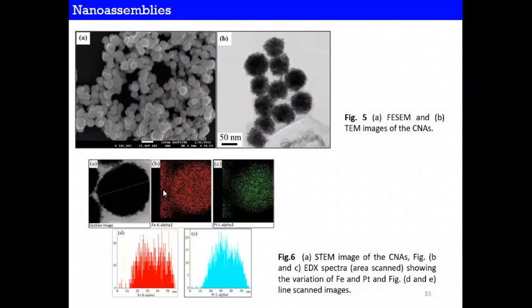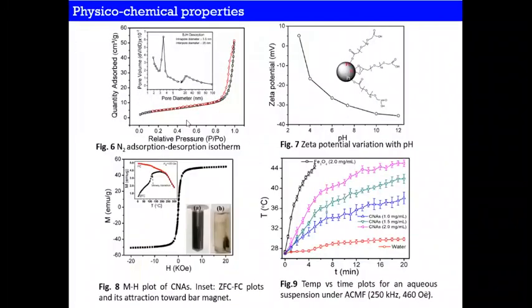So this is the formation of iron, platinum, and iron oxide; this is iron and this is platinum. We have taken the line scan in the STEM image, and it has been found that the iron and platinum are distributed throughout this material. This is quite porous, and this is the porosity measurement. The porosity measurement says it is mesoporous, with an interparticle pore of around 25 nanometers and an intraparticle pore of 3.5 nanometers. And then you can see the zeta potential at normal pH.